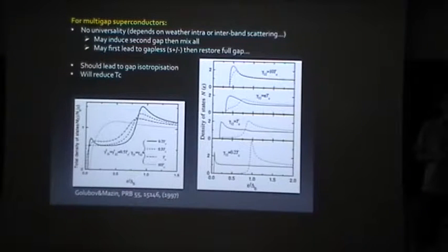Oh, no, that was related to the MgB2 part. The phonon has a self-energy effect that can be measured directly. We saw it from that, and lambda can be extracted. It mainly couples to the sigma band indeed. And from the collective mode, you can derive the interband interaction, and indeed it's an attractive channel. You can find out the sign from that, so it is S+S+. You can confirm that. And the numbers turned out to be right on the money with the estimates, both for coupling to the phonon and the interband.